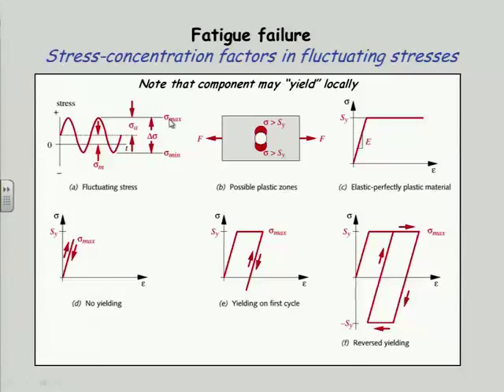If I exceed the yield strength, S sub y, with my sigma max, then I'll do some yielding. That's shown in the center bar here, center picture. So I run up the elastic curve and I exceed the yield strength of the material, and it moves over in strain. And when I relax the load, it comes back down a new line parallel to the elastic region, and I now have a permanent set. The set now you recognize is local. It's just in here. So the hole maybe got a little egg-shaped. It didn't affect the overall shape of the part, so I don't even notice it.